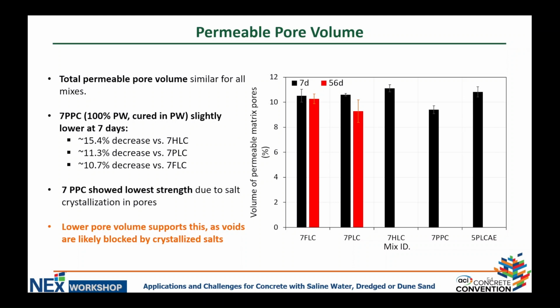And here we can see the porosity results, or permeable pore volume. I think I mentioned that, ASTM C642, where we are measuring the porosity of hardened concrete. So we can see that almost all the different mixes are doing the same. They are very comparable. The only difference is that the 7PPC mix, again, the mix that was made and cured in produced water, has a slightly smaller value for the porosity.